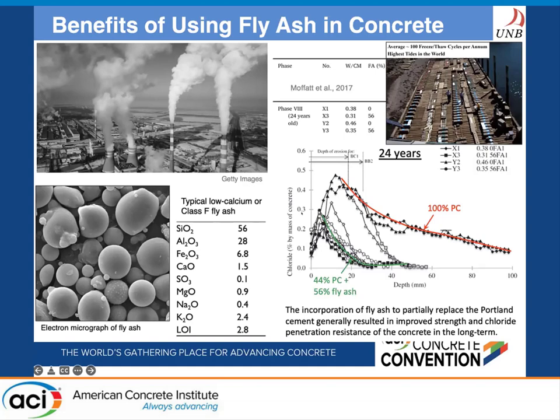A study was done to determine the long-term performance of fly ash samples. Samples were produced with and without fly ash and exposed to a marine environment for 24 years. They were brought back to the lab and tested for chloride concentration at different depths. The control mix — 100% Portland cement — had chlorides penetrated more than 100 millimeters, whereas the mix with fly ash had chlorides penetrated only up to 30 millimeters, a decrease of over 70%.